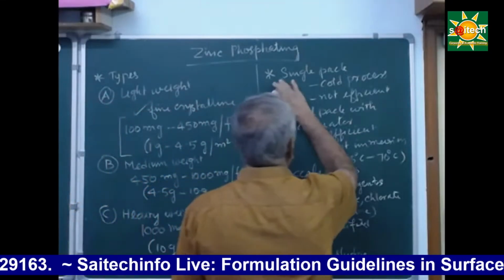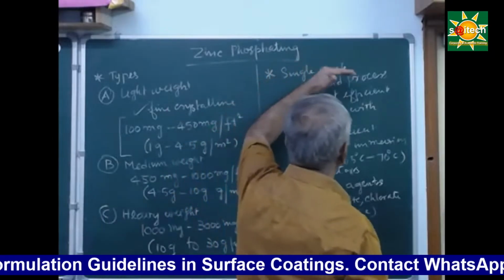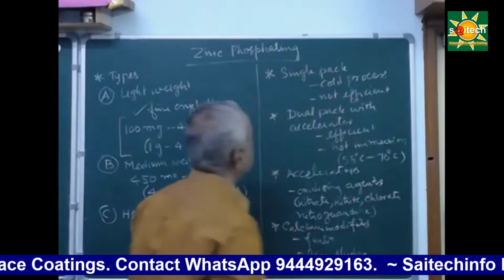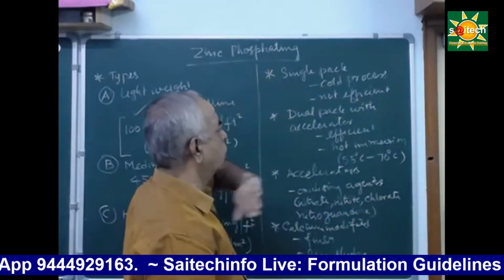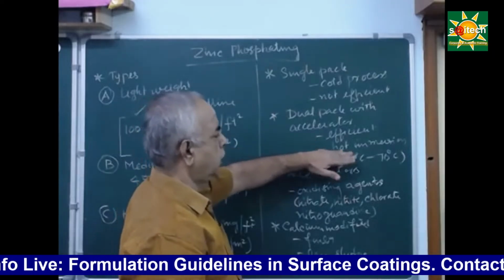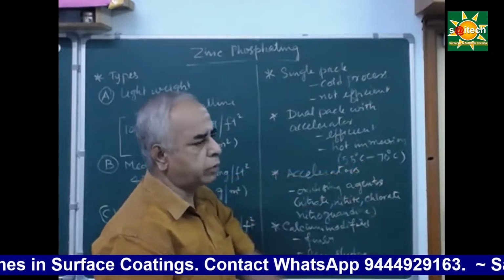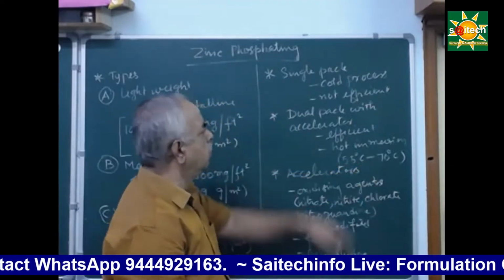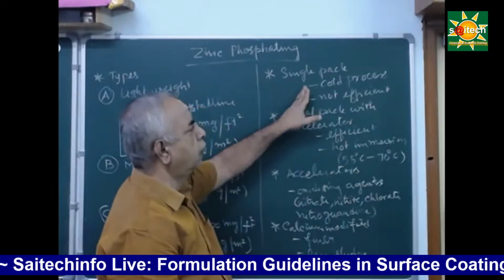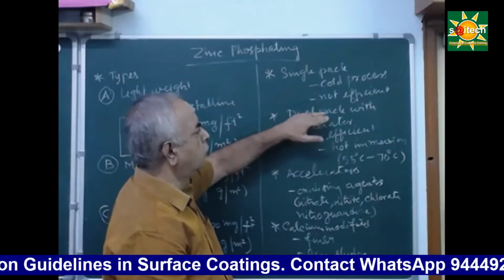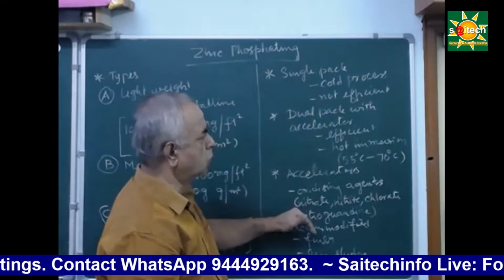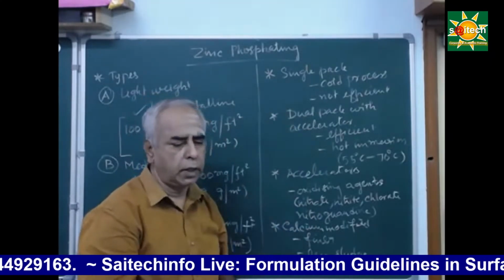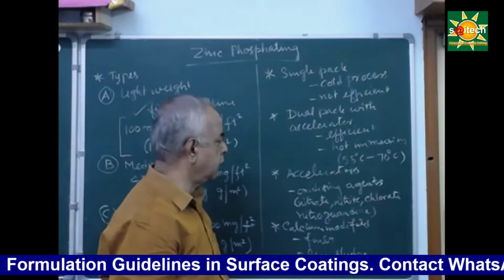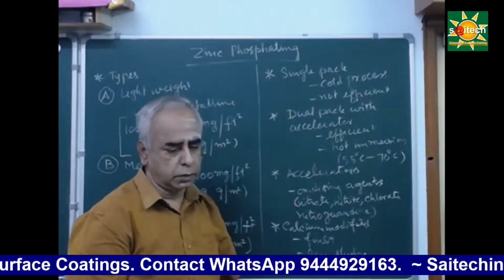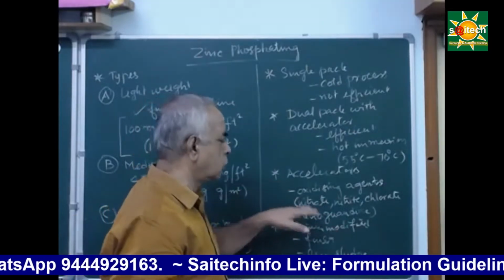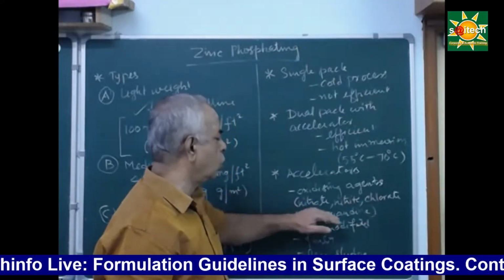Now, apart from that, we can have a single pack phosphating system or dual pack with the accelerator. In my opinion, always go for dual pack with the accelerator. Of course, heat energy is required, around 55 to 70 degrees centigrade, but that is the ideal phosphating. As far as the cold process is concerned, it will take a longer duration, and not only that, it is not as efficient as the dual pack also. The better crystal lattice pattern can be achieved only at 55 to 70 degrees centigrade by using appropriate accelerators. Accelerators are nothing but oxidizing agents like nitrate, nitrite, chlorate, nitroguanidine, etc.